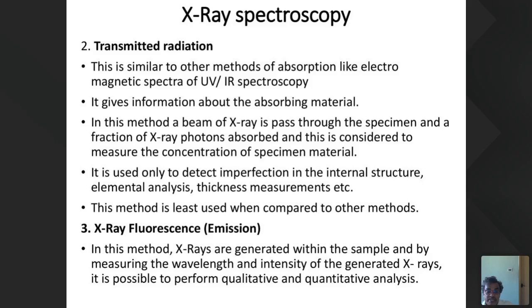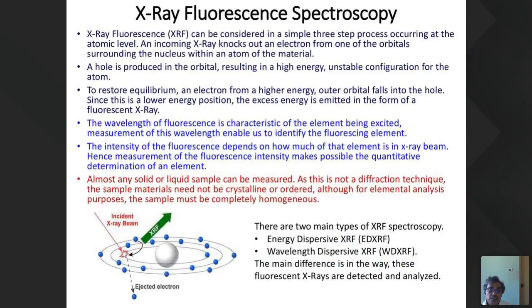X-ray fluorescence. In this method, X-rays are generated within the sample, and by measuring the wavelength and intensity of generated X-rays, it is possible to perform qualitative and quantitative analysis. X-ray fluorescence can be considered a simple three-step process occurring at the atomic level. The incoming X-ray knocks out an electron from one of the orbitals surrounding the nucleus within an atom of material. A hole is produced in the orbital, resulting in a high energy, unstable configuration for the atom. To restore the equilibrium, an electron from a high energy outer orbital falls into the hole. Since this is a low energy position, excess energy is emitted in the form of fluorescence X-ray.